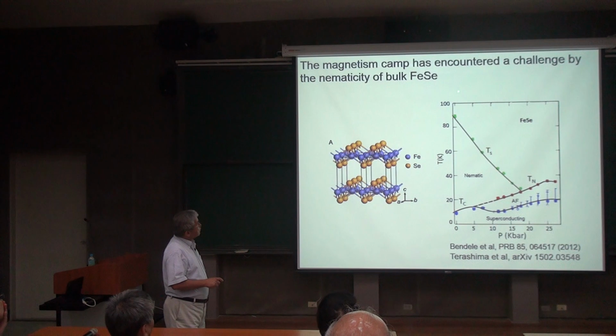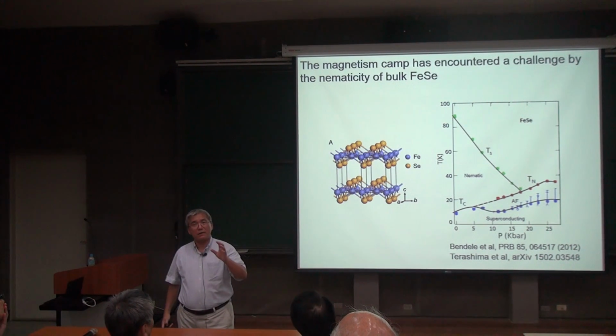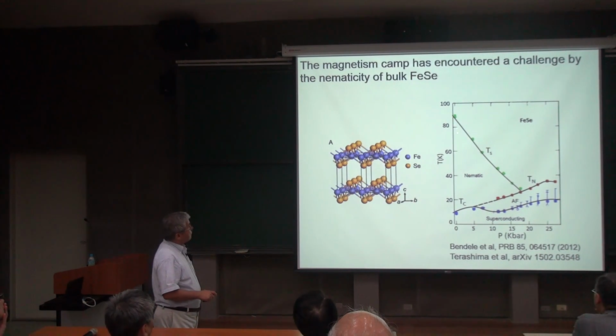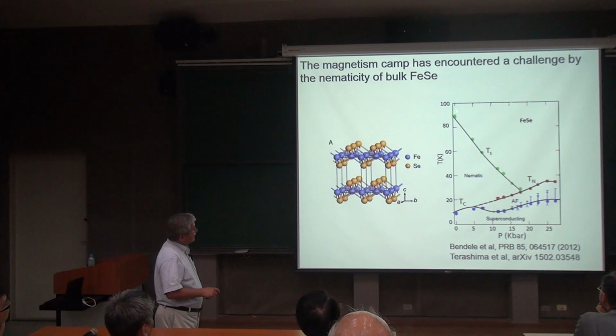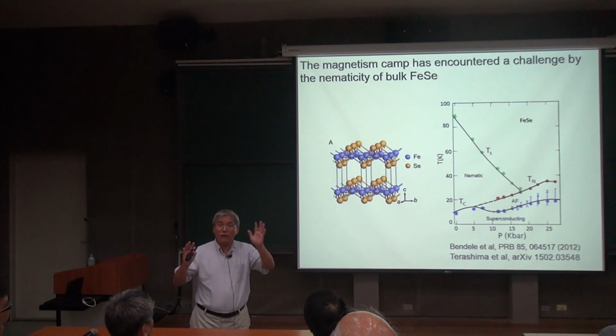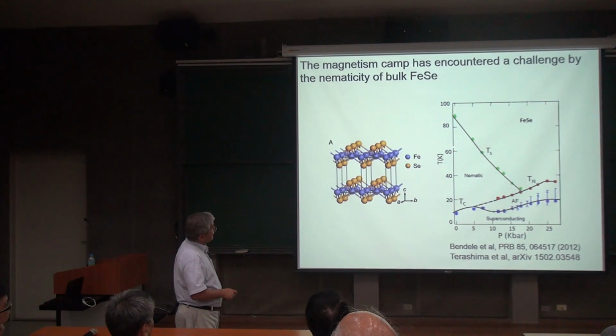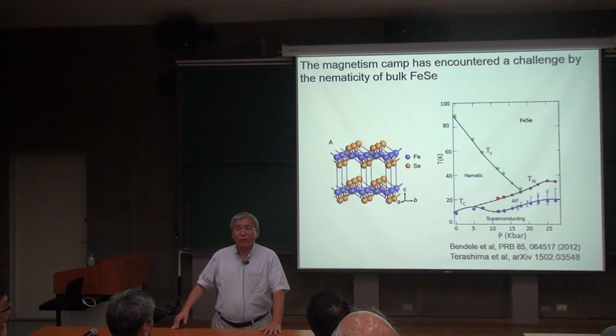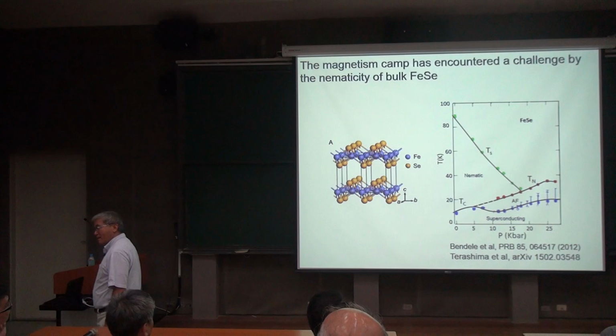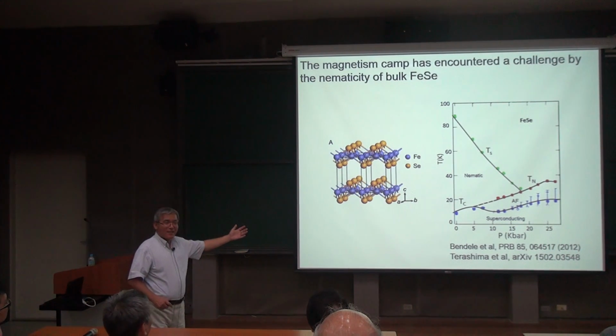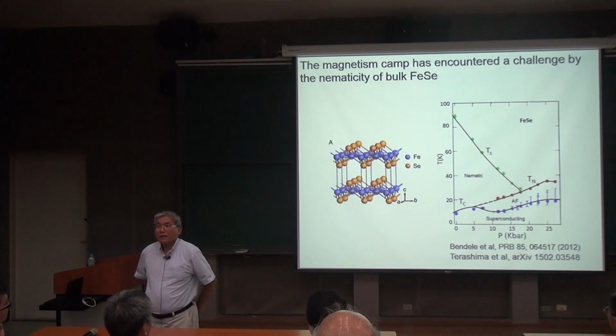So at ambient pressure, when you lower temperature, this solid line represents the structure spontaneously distorting from a square to a rectangle. So that means the 90-degree crystal rotation symmetry is spontaneously broken here. But the neutron scattering study has told us that below 90 Kelvin, here is the 8 Kelvin superconducting transition, there's no magnetic order whatsoever. Not only is the magnetic phase transition not close to the structural phase transition, there is a non-magnetic state. So at this point, the orbital school really revived. They say, look, this clearly is telling you that magnetic interaction has nothing to do with nematicity.